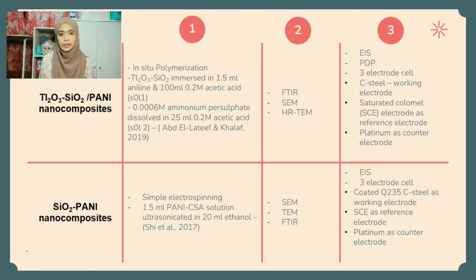Both of the nanocomposites use the same characterization methods, which are Fourier transform infrared spectroscopy, scanning electron microscopy, and transmission electron microscopy. Thallium trioxide silica polyaniline nanocomposite uses two methods for corrosion analysis, which are electrochemical impedance spectroscopy and potentiodynamic polarization. Both approaches were carried out in a typical three-electrode cell, with carbon steel as the working electrode, saturated calomel electrode (SCE) as the reference electrode, and platinum sheet as the counter electrode. Only electrochemical impedance spectroscopy was used to investigate the electrochemical behavior of uncoated and coated Q235 carbon steel in a three-electrode cell for silicon dioxide polyaniline nanocomposite.